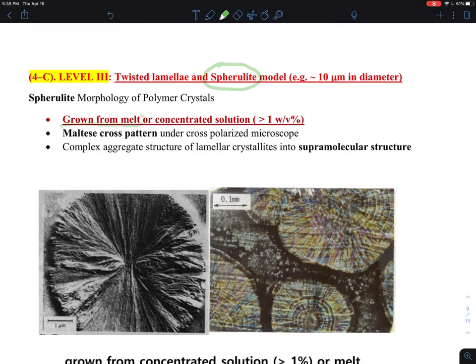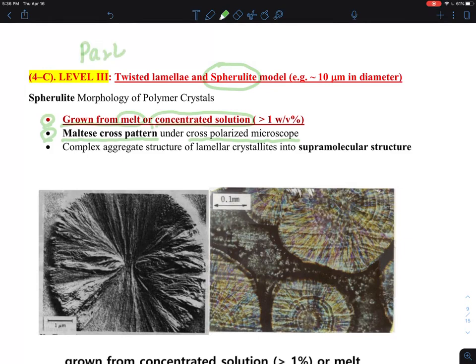Spherulite is usually grown from the melt, which is a polymer as it is, or a concentrated solution — not a very dilute solution, something less than 0.1 weight percent, where you can hopefully grow a single crystal. I'm going to show some evidence of the spherulite structures, including the Maltese cross pattern on the cross-polarized microscope. This is part C1, and in part C2, I'll talk about the multi-scale supramolecular structure within the lamellar spherulite.